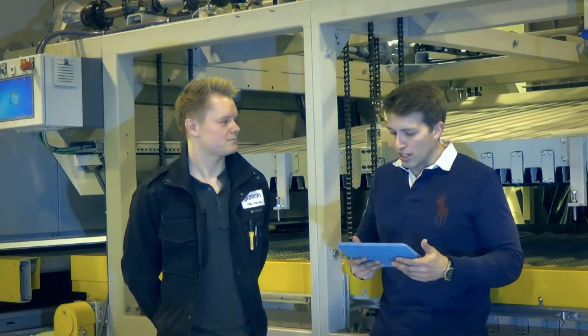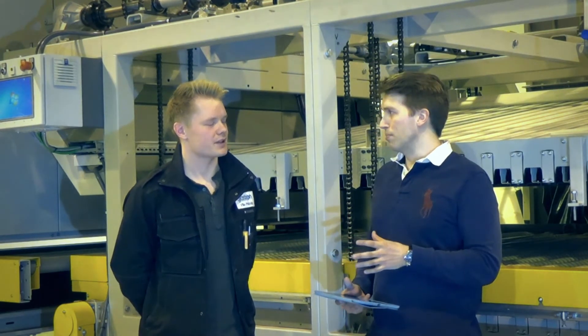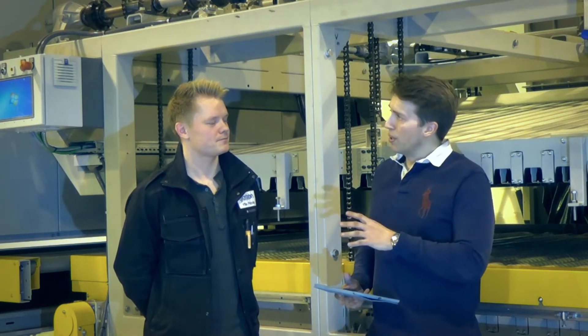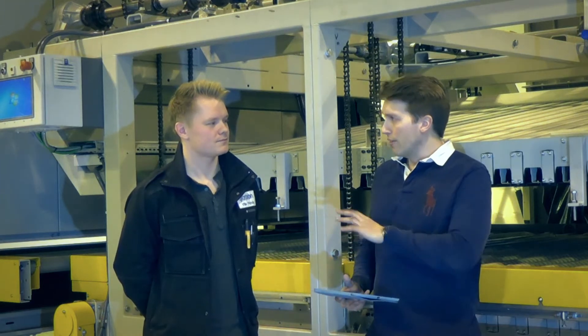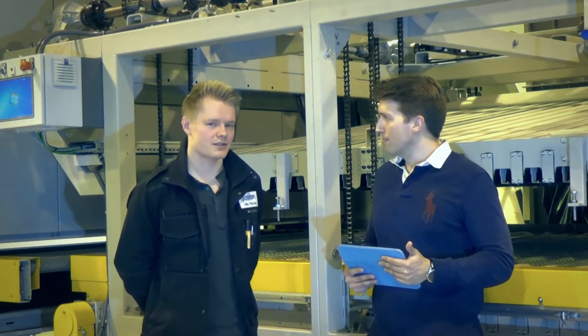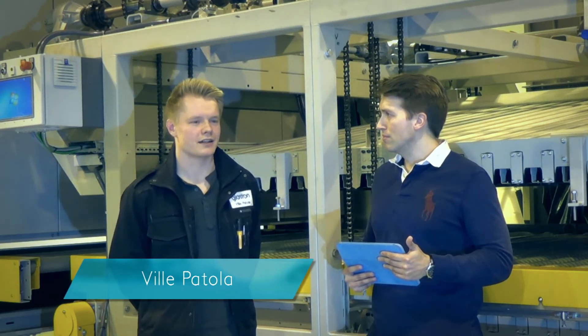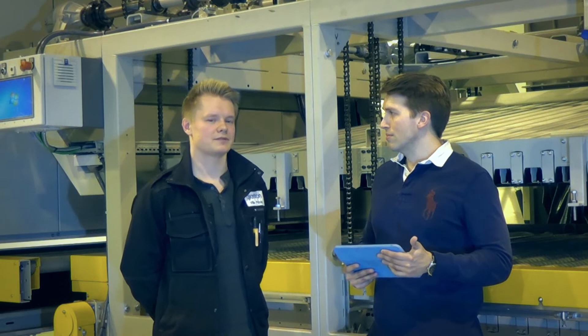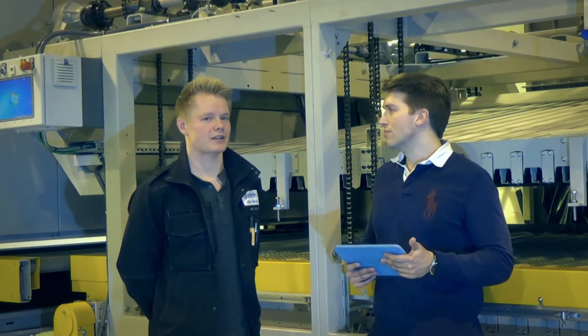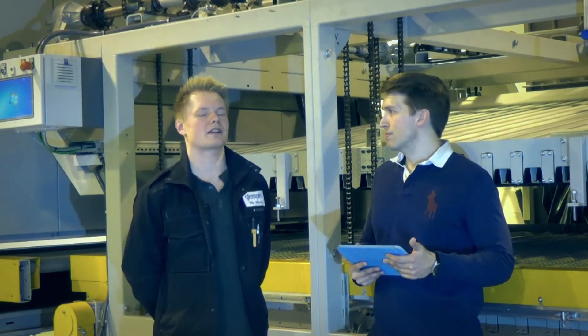I have Ville here, our process expert. We have the tempering process and we have the heat strengthened glass. Is there a difference in your opinion on the quality in either of these two, and if there is, why? Well, it's all about temperature — the exit temperature of the glass. I see no difference in quality in both cases. There might be in theory some difference in heat strengthened glass due to longer cooling time, but practically there's no difference.